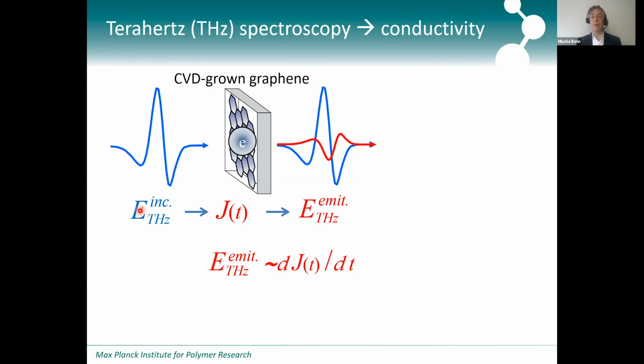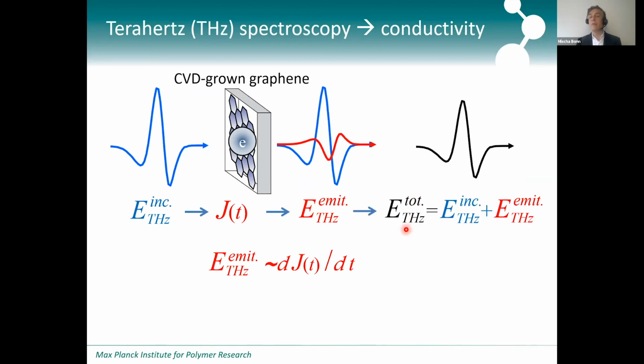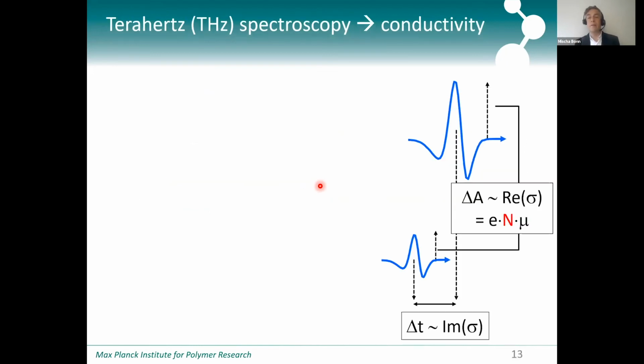And so we'll have an incident field that is transmitted, and then an emitted terahertz field that originates from that current, and those two will interfere. And so we have a total terahertz field, which is the sum of those two. And so we can backtrack from this black curve here, and comparing it to the blue curve, we can infer this red curve. And this red curve is what tells us how the field induced the current. So we can backtrack the current, the time-dependent current, from that trace here, and that tells us, of course, about the mobility and the number density. So that is the physical idea behind the measurement.